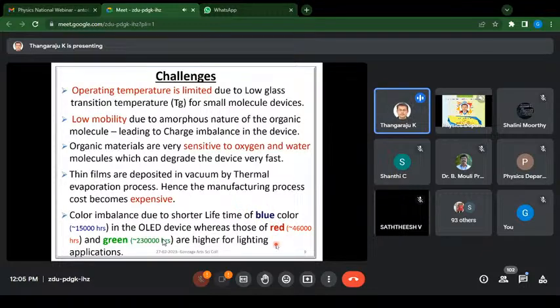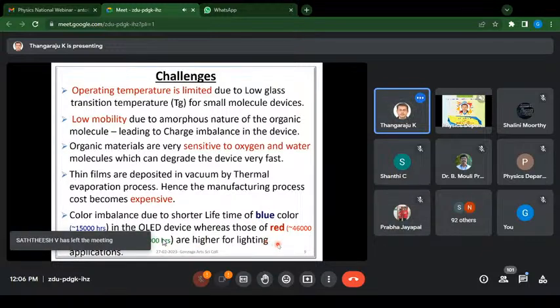And very importantly, color imbalance. To make the white light source, we need to have the three primary colors: blue, green and red emitting organic molecules. Because of the wide band gap, the blue emitting organic molecules have a very short lifetime. And when we make these white light sources, the blue light emitting organic molecules will deteriorate much faster than the other organic molecules, and hence the color purity will go bad within a short time.